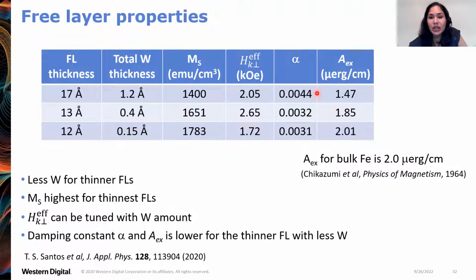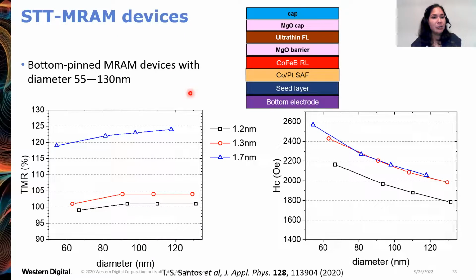The damping parameter was already low to begin with. By taking out this heavy metal, we reduced it even further. And the exchange constant A increased so that it approaches values we know for bulk iron. So this is to show that these very thin free layers have very good magnetic properties. So we proceeded to make bottom pinned STT-MRAM devices with this free layer thickness ladder. The diameter of these devices using optical lithography is in the range of 55 to 130 nanometers, and the TMR values approach 125%. And the coercive field for switching the free layer, switching the MRAM bits, reached 2.6 kilo-oersteds for the smallest devices.